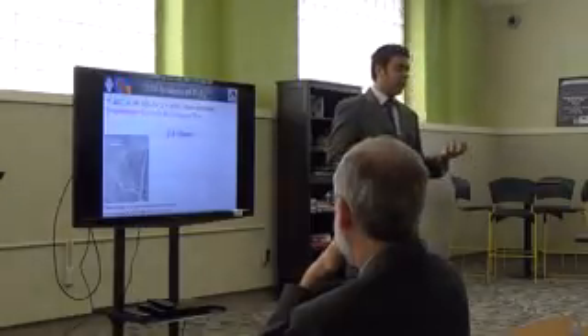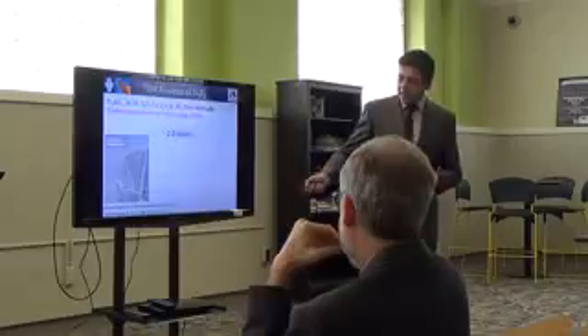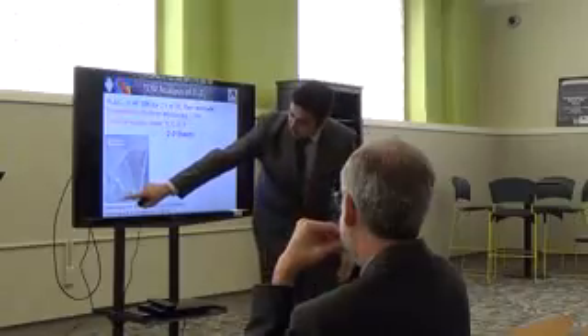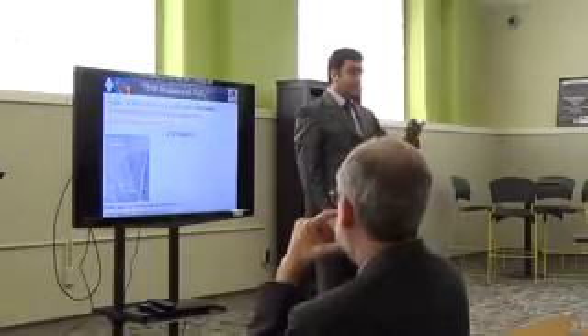We did sonication, and then we did transmission electron microscopy. Transmission electron microscope can go to much higher magnification than scanning electron microscope. And you can see here, this is a sheet of titanium. The chemical composition shows titanium, carbon, oxygen, chlorine. And I'm not sure if you can see it or not, but it's electron transparent. You can see the carbon grid underneath, so it's very thin.